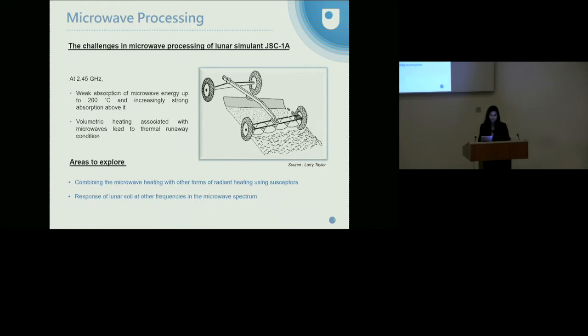Another issue is that the microwave is preferentially absorbed by the inner portion and the surface stays less heated. And due to these factors, many researchers have proposed to combine the microwave heating with some other form of radiant heating using susceptors. The other area where not much research has been done is to find out the other frequency in the microwave range where we can heat the lunar soil efficiently. Till now, the researchers have only worked with the kitchen microwave frequency, which is 2.45 gigahertz.